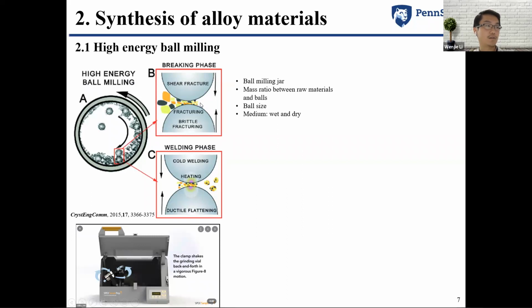So it breaks the raw materials, and high energy ball milling can generate heat when the materials contact with the balls. For some of the alloy materials, it can directly form the desired phases, which is also called mechanical alloying. But for most of the alloy materials, this technique is used to generate nano powders, which can be further used to synthesize the single pure phase or any desired phase of the alloy materials. The uniformity and how well we can prepare alloy materials using high energy ball milling depends on the ball milling jar.